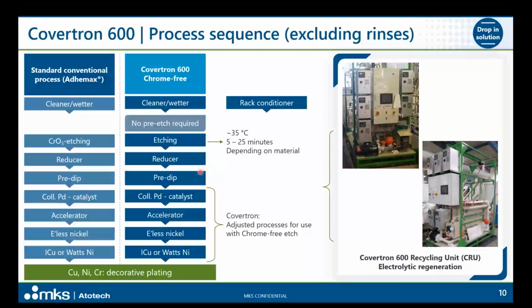The rest of the pre-plating process steps will be exactly the same as you currently have in your line with the benchmark process, with some potential minor adjustment for use with chrome-free etching. Of course, as there is no Chrome 6 in the pre-plating steps, you know that the hexavalent chromium, besides its etching properties, also works to prevent rack plating. With Covertron 600, we don't have any chrome at all. So what is recommended, to prevent any rack metallization, is the installation of a rack conditioning step.